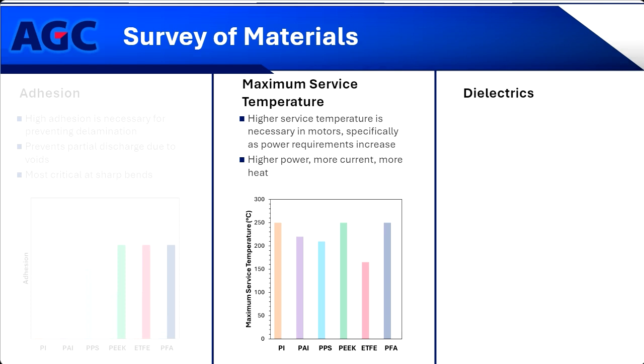So yes, we want to increase the voltage, but as I mentioned, it's going to be a balance of increasing both current and voltage. So what I show here in this graph is that the majority of these materials have a maximum service temperature above 200 degrees Celsius. Usually that is the minimum needed for these electric motors.